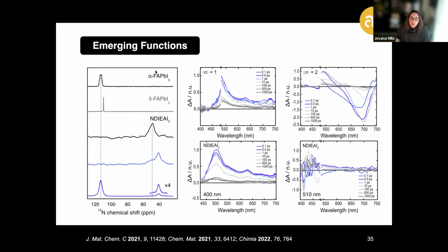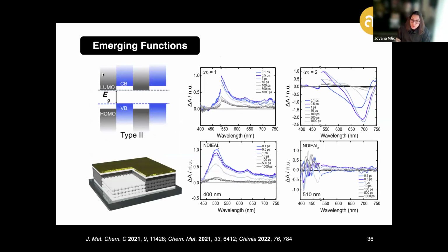More importantly, in these materials, apart from structural level interactions enabling stabilization, electronic interactions and exchanges were particularly relevant, analyzed using transient absorption spectroscopy that reveals the emergence of a signal around 550 nanometers, particularly upon excitation at around 500 nanometers, corresponding to a naphthalene diimide or NDI radical anion, which cannot be generated upon excitation of the neat organic component under these conditions, and which requires electronic exchange between the inorganic and organic phase to actually appear in the hybrid structure.